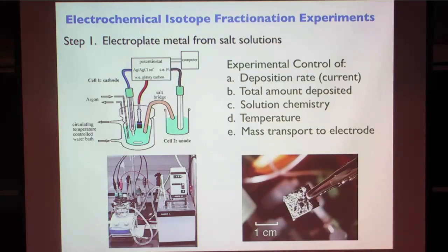And we run an electroplating reaction in which we fill a solution, which is about the size of our coffee mugs, with a salt solution, a supporting electrolyte, and then electroplate a very, very small amount of metal. So for example, in some of the reactions we'll see, I actually don't remember if that's iron or zinc, but a small amount of iron +2 in solution will be electroplated on the electrode. We'll pull it out of solution and then do a measurement.